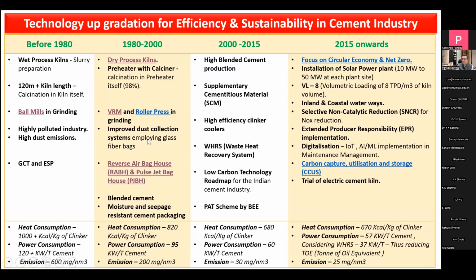As we kept on increasing the stages of the preheater, the heat transfer happening between the material and the gas improved, leading to better efficiency. Along with the process efficiency of the preheater and calciner, a lot of changes were done on the grinding aspect. Like we came up with the vertical roller mill and roller presses.